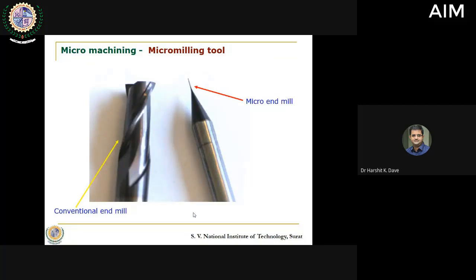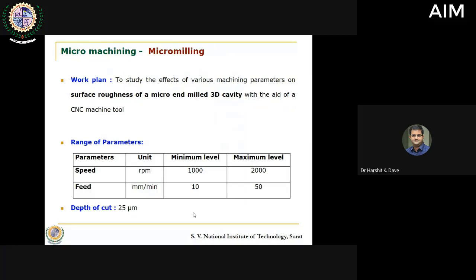But you can see if you compare a conventional end mill cutter with a micro end mill cutter, the dimension is quite clear from the image itself. In the micro domain, say 0.5 mm diameter, it would be quite smaller in size. What we tried to do was create a micro 3D cavity with the help of micro milling, and we used our desktop CNC machine that we had. On that machine we carried out the same task.